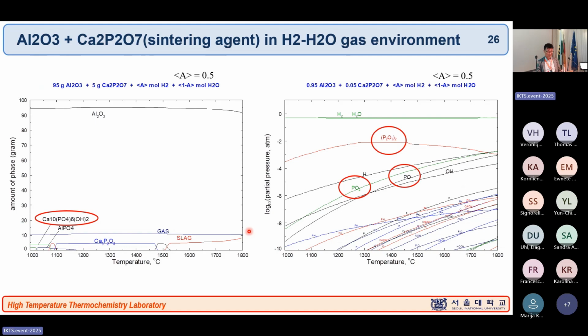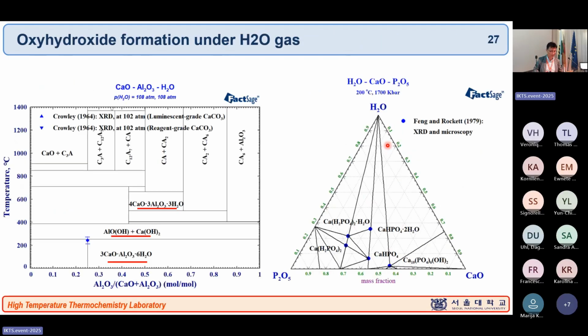And then of course, if you are increasing temperature at the 0.5 condition, you can see all kinds of calcium phosphate, P2O5 or PO gas phase formation too. So this is the degradation of your bond material. Then it means your refractory's strength will be gone. So you actually have the degradation automatically.